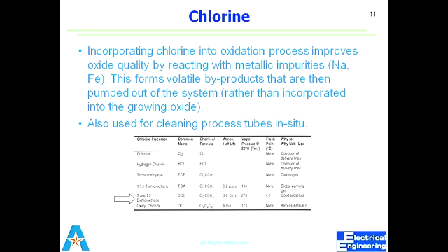Chlorine gas can be used to provide chlorine, but the problem is that it's very corrosive, and due to the corrosion process, if we supply chlorine gas, it takes those corrosive impurities with it towards the furnace. It will corrode the internal side of the pipelines or of the cylinder or anything. So chlorine as a gas is not a good source. So the problem is corrosion of delivery lines.